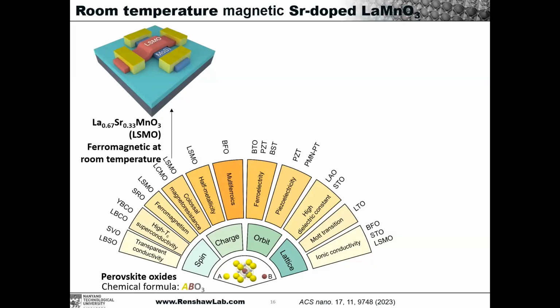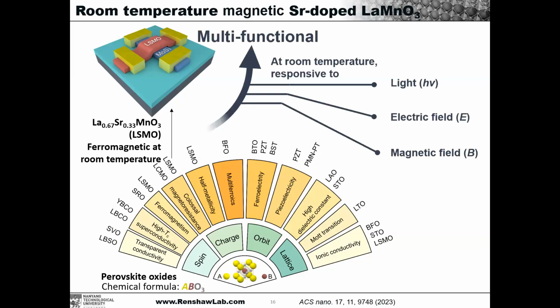This means the magnetoresistance is very high. And of course, it's a perovskite. That means we can fabricate them into the oxide freestanding membrane form. And what I'm going to discuss is we use the MoS2 and the LSMO, combine them together, make a heterostructure, and we can achieve a multifunctional device that can respond to light, electrical field, as well as a magnetic field at the same time. And the device works at room temperature on silicon or silicon dioxide substrate.